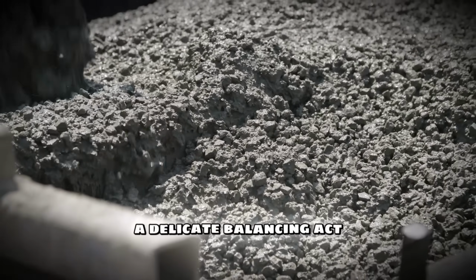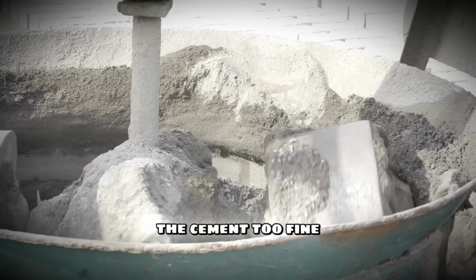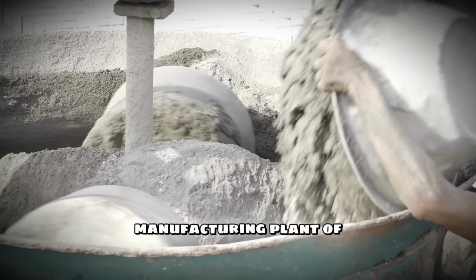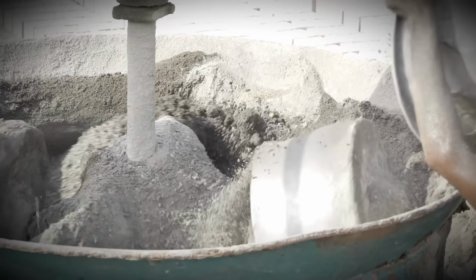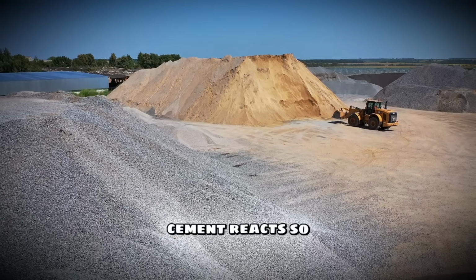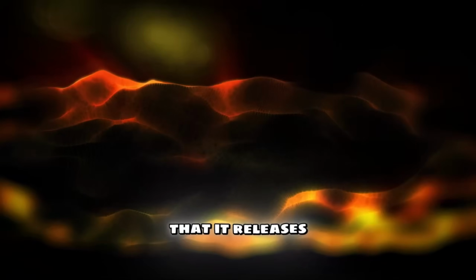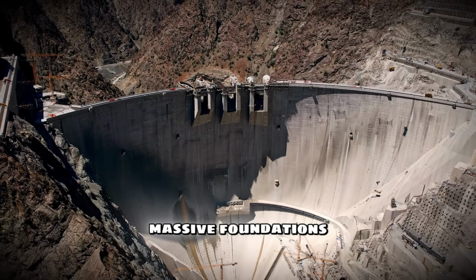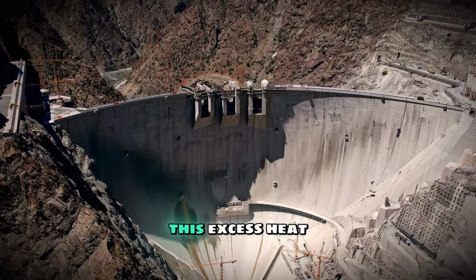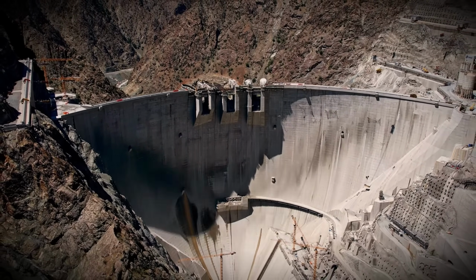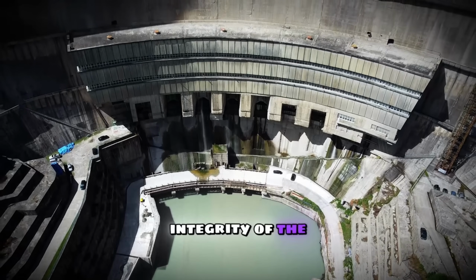But it is a delicate balancing act. If you grind the cement too fine, it costs the manufacturing plant a fortune in energy. Worse, ultra-fine cement reacts so violently and quickly that it releases a massive amount of heat, known as the heat of hydration. In large pours like dams or massive foundations, this excess heat can cause severe thermal cracking, compromising the structural integrity of the entire build.